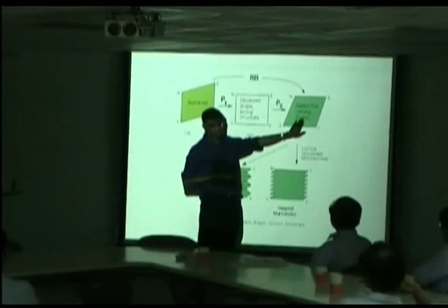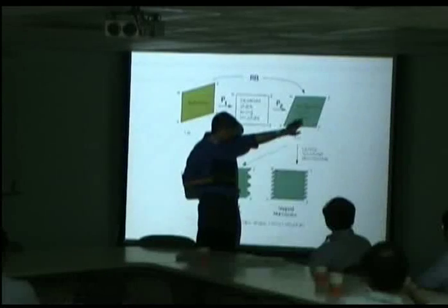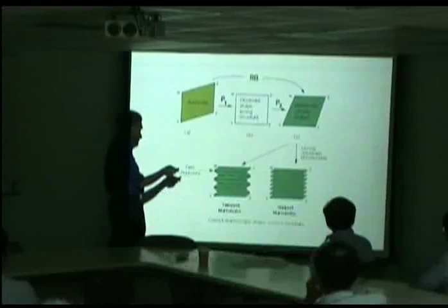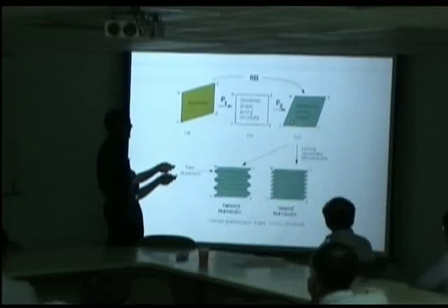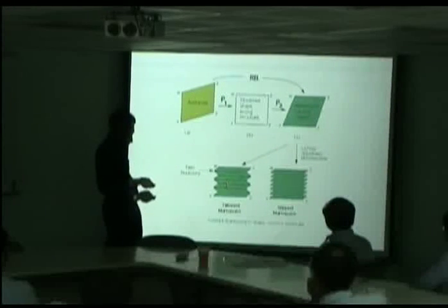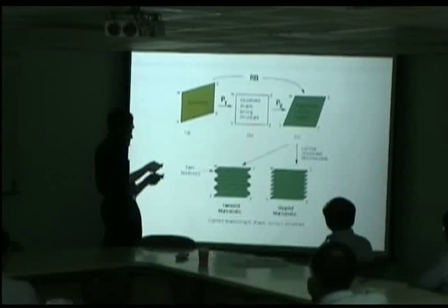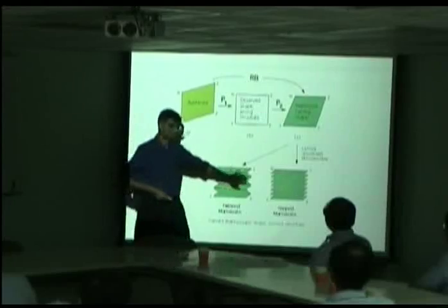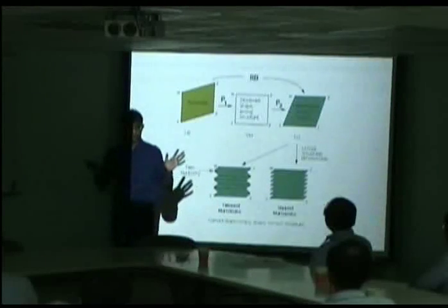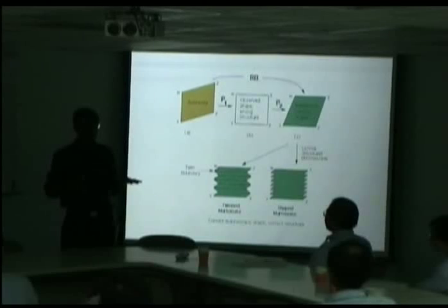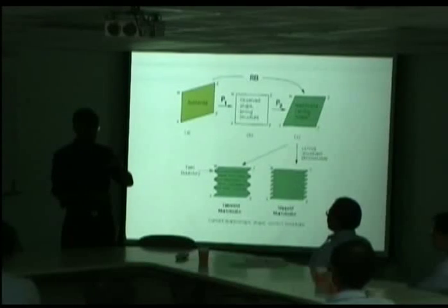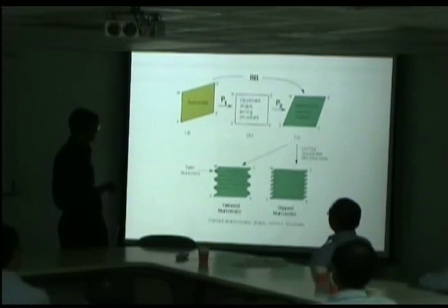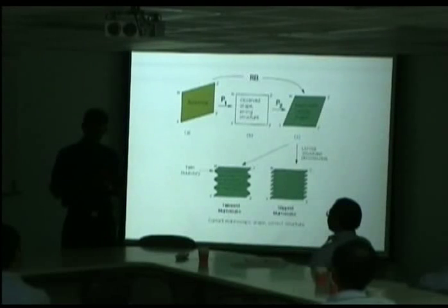I can alter the shape without altering the crystal structure by periodically slipping the crystal. So the macroscopic shape here is correct and the crystal structure is correct. Or I can periodically twin it to produce the correct macroscopic shape and the correct crystal structure. And that's why we see twins inside martensite or slip steps. Okay. Now we have the complete theory that we can predict the orientation relationship by doing the Bain strain and the rotation, which gives an invariant line. And the macroscopic deformation is a shear.